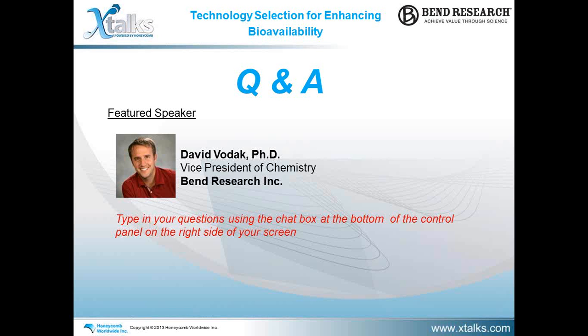Highly is kind of a subjective term, as well as soluble, I guess. I think the polymers that we're using, you could have a whole webinar on just the polymers that you would use and select. One of the nice things about some of the ionic polymers that we talked about is that in the solid state they're protonated and relatively hydrophobic, which limits the amount of water that formulations pick up and therefore can lead to better physical stability, whereas some of the neutral polymers may pick up more water. In all cases, when the materials hit pH 6.5, they should rapidly dissolve into, at the very least, colloidal systems where the drug's able to release or interact in a high energy fashion.